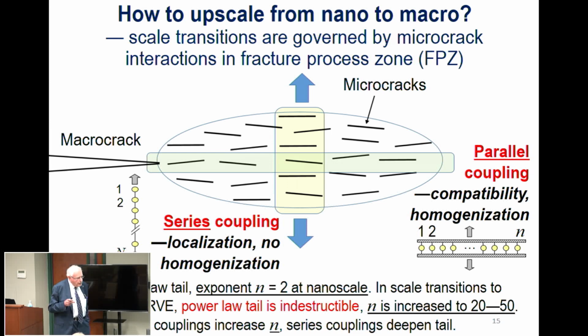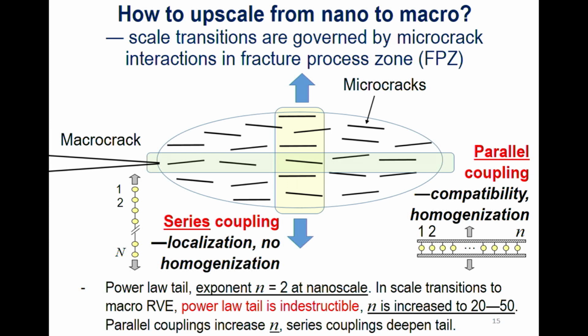So how do we increase the exponent from 2 to 60? And that's because of scale transitions. Now in scale transitions, what do we have? We have a macro crack, it is a process zone that has many micro cracks. Each micro crack is a process zone much smaller, that has again many micro cracks, and so it goes. In concrete it goes 7 orders of magnitude, in metals about 4 orders of magnitude.